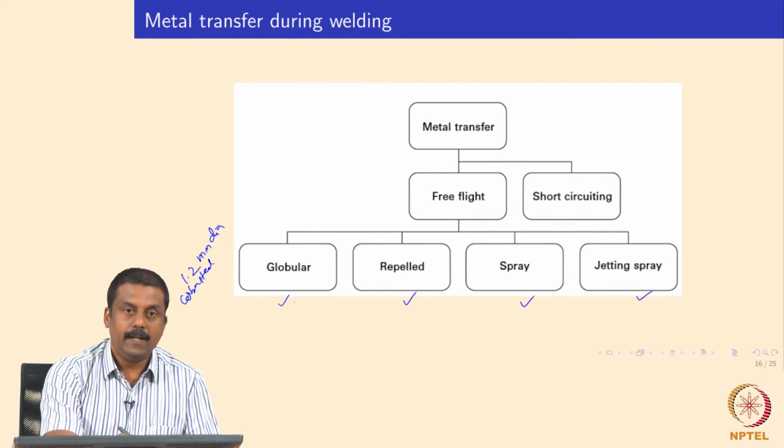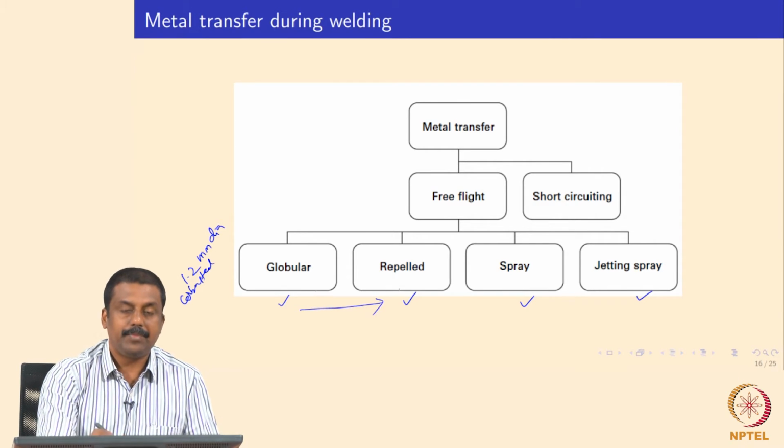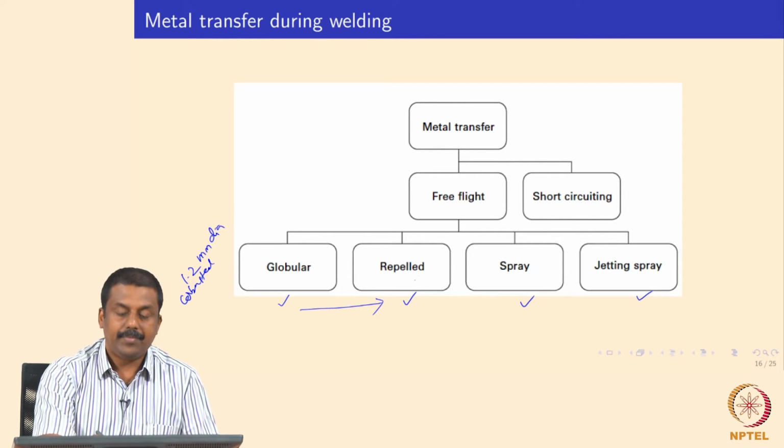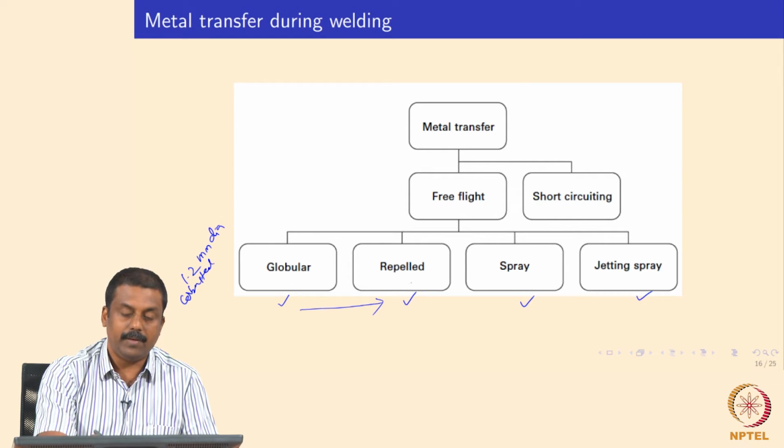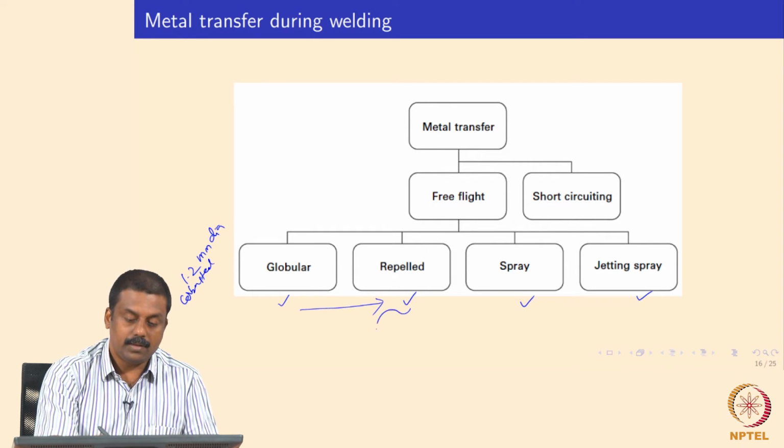The moment the droplet has grown in size, obviously the gravitational force can pull the droplet in a globular format. So if you increase the current slightly, you also generate some Lorentz force, and because of increasing current, you may also tend to vaporize. So both increasing Lorentz force lead to a generation of local magnetic field, which can repel the shape of the droplet from complete globular to a shape like the shoe of a buffoon in a circus. So something like this.